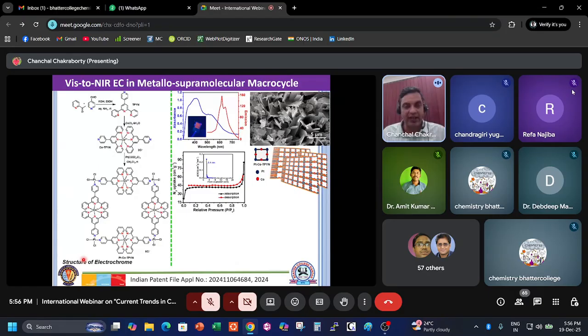So the ligand plays the role of giving this square complex structure, which gives better ion movement. Another thing is the metal to metal electron transfer through electron hopping in this kind of nanosheet structure, which I showed earlier. This gives some aggregation inside the material. And by a DFT study, we established that platinum has a d-pi-p-pi bond with the ligand nitrogen, and as a whole the complex is electronically delocalized. That is also important for any pseudo-capacitance or Faradaic material, where electron transfer is required for faster